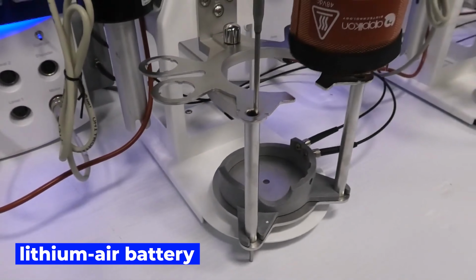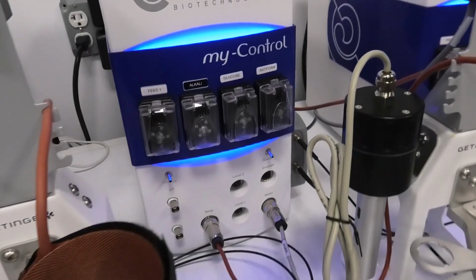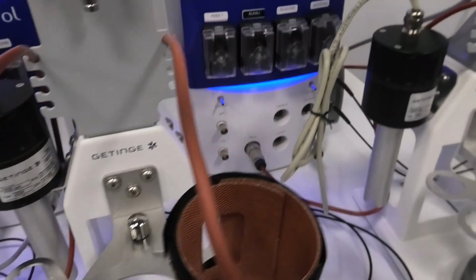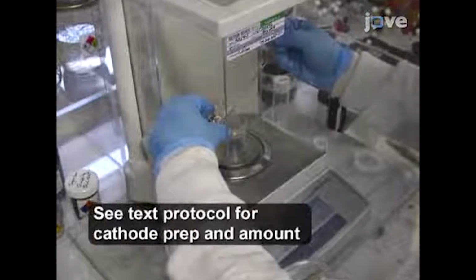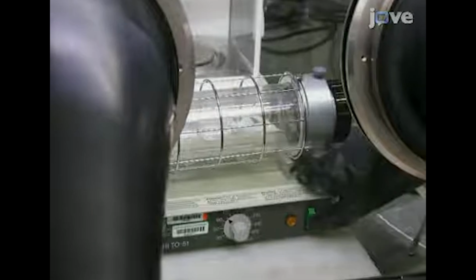On the other hand, a lithium-air battery breathes the atmosphere, which is only about 21% oxygen. The rest of it is the problem. Water vapor and carbon dioxide react with the lithium and leave deposits that block the pores in the cathode. Although the chemistry was proposed in the 1970s, that single difference is why it took until 2018 for anyone to build a cell that could breathe ordinary air.